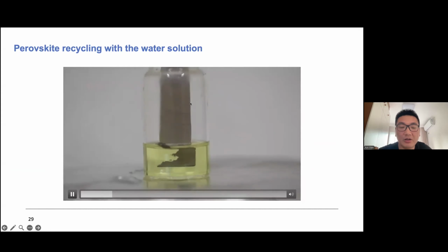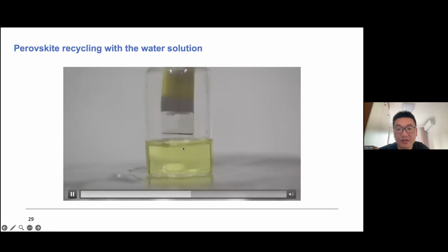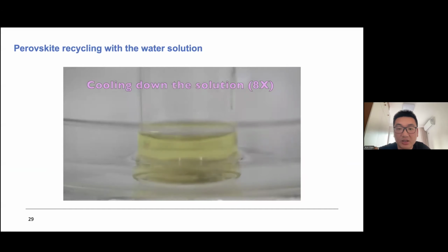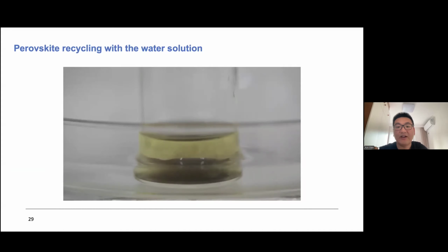This is how we demo the recycling of the solution with water. This is the pure water solution with the three additives. And then we can put the perovskite films into it. And if we remove the substrate layer and we cool it down, the perovskite crystals can self-precipitate very quickly. And we also checked the crystallinity and the quality of the perovskite. It's high quality because it's a kind of crystal growth process.